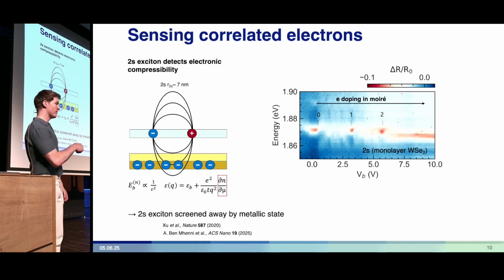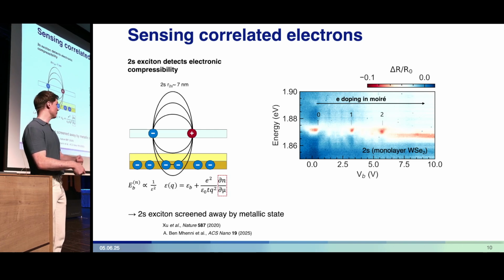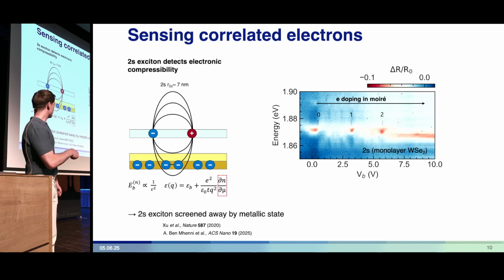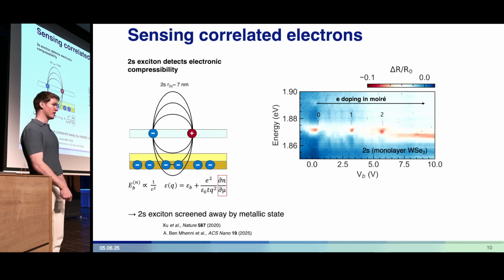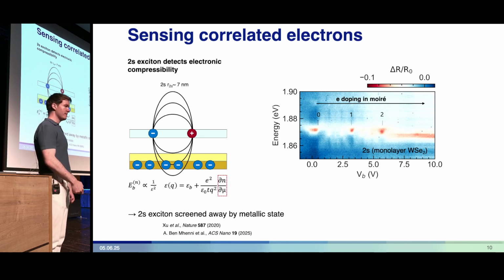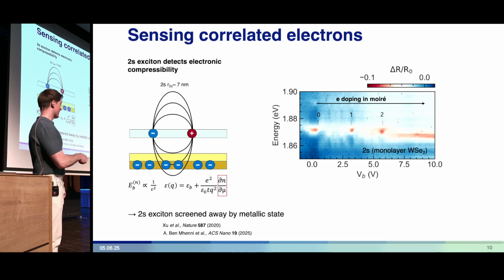This is the spectrum of the 2s exciton as a function of increasing electron doping in the Moiré layer, while the monolayer itself is charge neutral. I've labeled some particular points where you can see there's a strong exciton signal from the 2s exciton. These correspond to 0, 1, and 2 electrons per Moiré unit cell, so these are integer filling insulators residing in the Moiré layer.